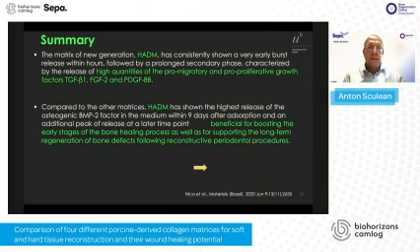PDGF-BB. Compared to the other matrices, HADM has shown the highest release of the osteogenic BMP2 factor, because this was a very important observation and may bear also clinical relevance.